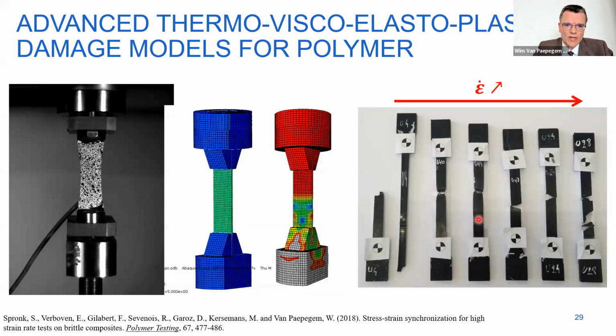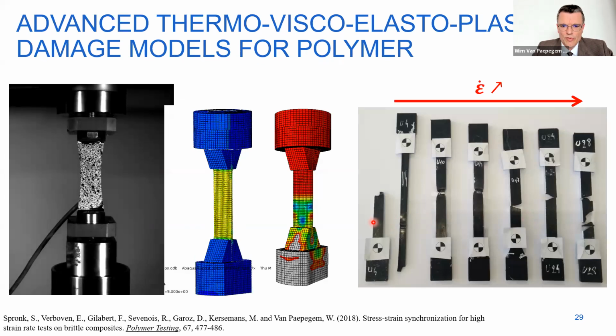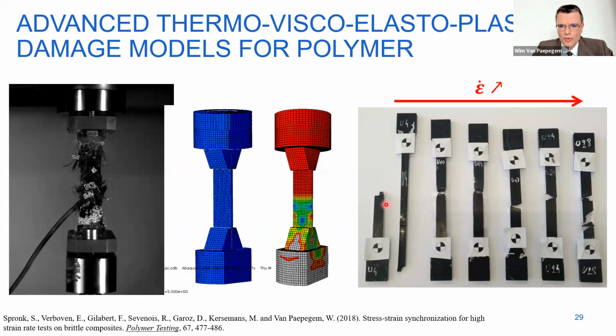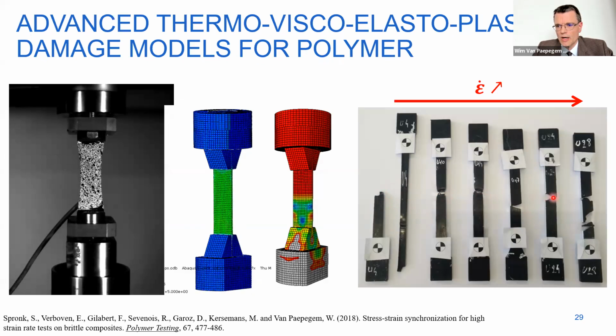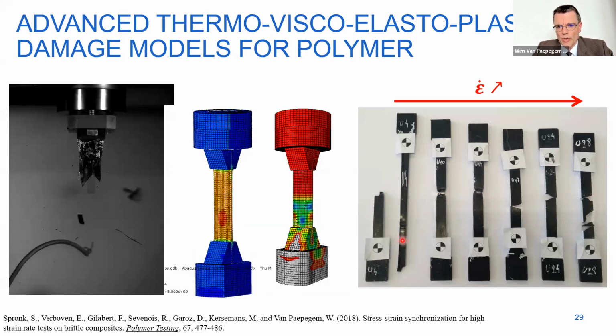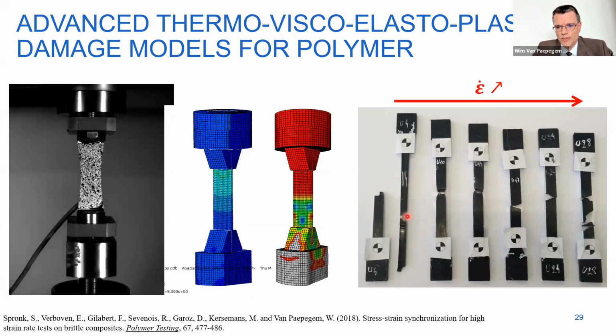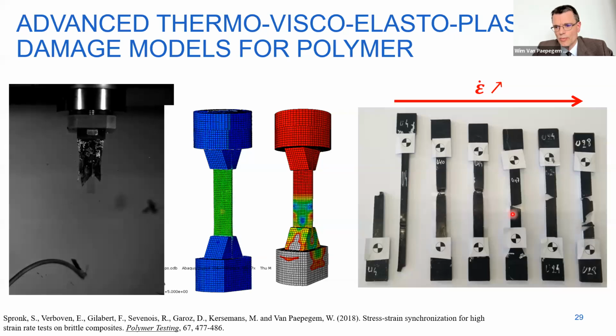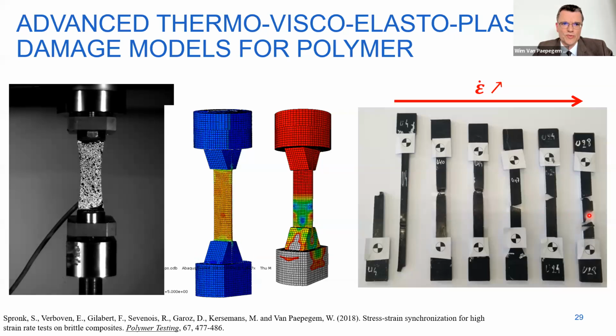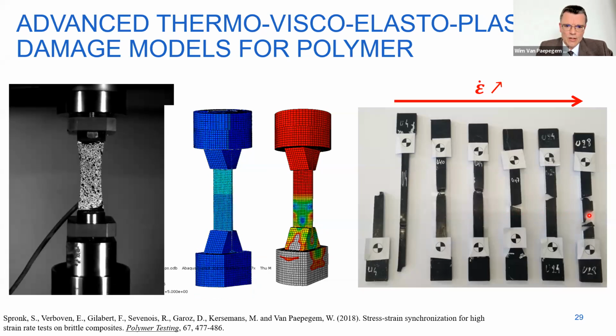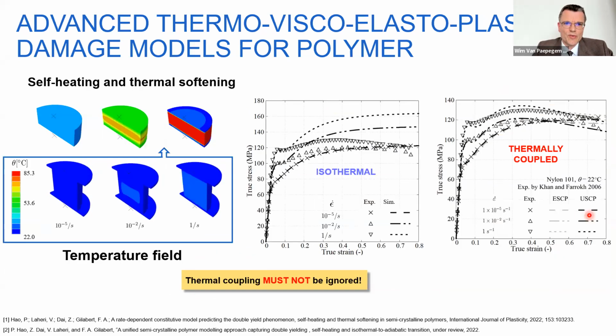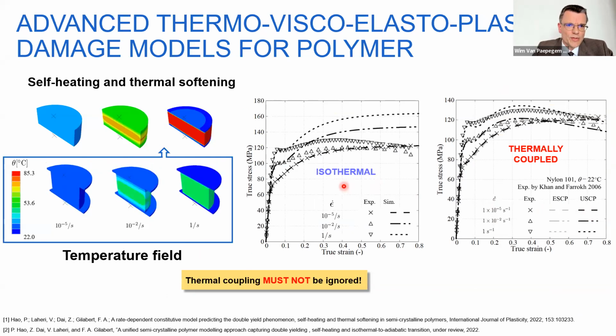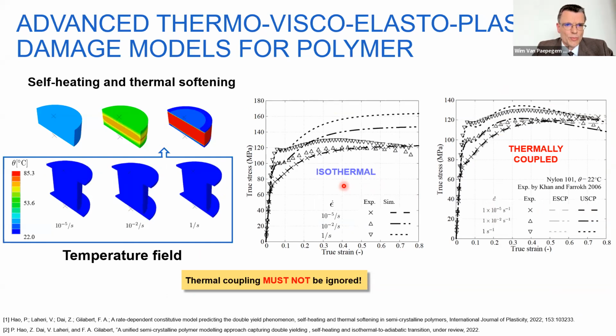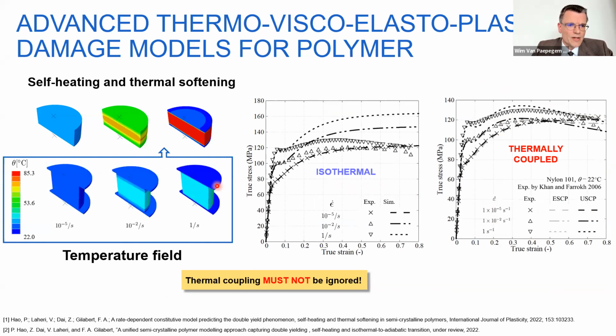And then we also have strain rate dependent testing. You see here for that same polyamide 6, if you start from static loading up to very high strain rate, you see here this part is connected with this part, so it stretches really very long, and here it gets more and more brittle because of the strain rate effect. Why is this all important? If you calibrate your polymer model for the micro scale, you should not introduce any fictitious effects in the polymer that are physically not there. And that I want to illustrate with this last slide on the micro scale.